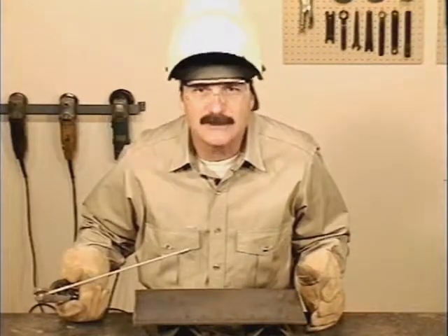If the amperage is set too low for the conditions, the puddle won't spread out, taking longer to tie in on the sides. The rod might stick or go out. If the amperage is set too high, the puddle is agitated and extremely fluid. Little balls of metal might dance off to the sides, causing excessive weld spatter.